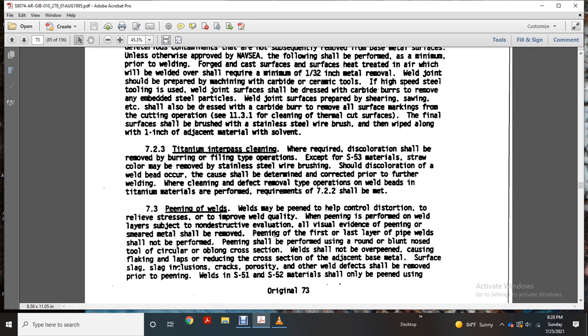When peening is performed on a weld layer subject to nondestructive evaluation, all visual evidence of peening and smeared metal shall be removed. Peening of the first and last layer of the pipe weld shall not be performed. Peening shall be performed using a round, blunt nose tool with a circular or oblong cross section. Welds should not be over peened, causing flaking or lapping, or reducing the cross section adjacent to the base metal surface. Slag inclusions, cracks, porosity, and other weld defects shall be removed prior to peening.